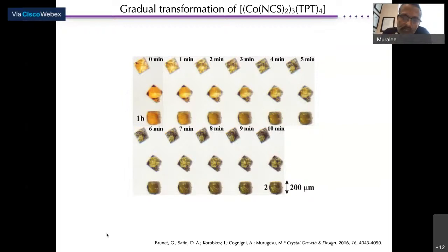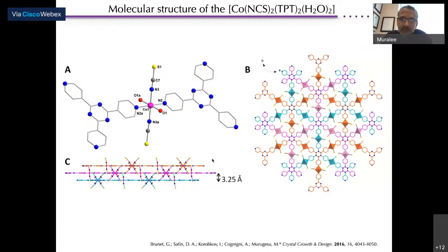You should be able to take the crystal out and put it back into a different solution to be able to soak it in. But as you can see in these pictures, within 10 minutes or even within 5 minutes, you see the color change of this cobalt MOF. And this color change leads to a decomposition. And by the time you reach above 6 minutes, it's completely amorphous in this system. So this was a bit disappointing for us, but we still wanted to understand the two-dimensional framework shown here.